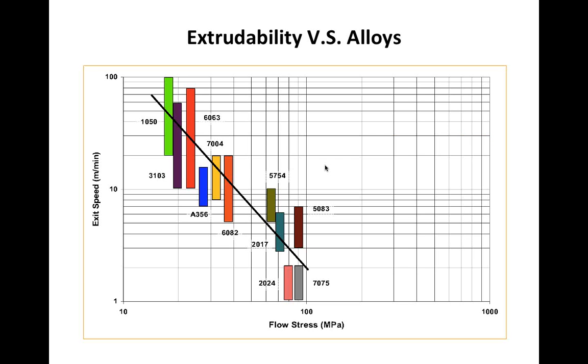So the graph shows all sorts of different alloys from 1000, 3000, up to 7000. And on the bottom of it is flow stress. You can see 7000 series alloys have a very high flow stress, so you need a very high pressure to push them around. And then they will not like to go through small spacings. That's why there's a minimum wall thickness for the 7000 series alloys.